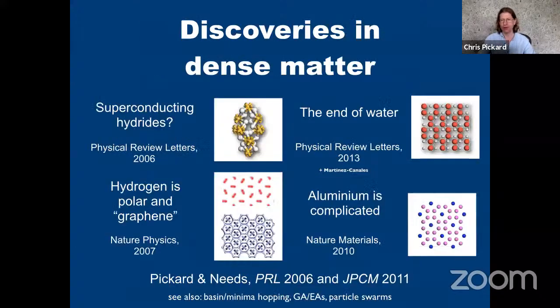So here's a sort of roll call of the early flush of success we had with this method. When we started out, it seemed like pretty much everywhere I pointed this code, I was finding new and surprising things. For example, we have generated probably still the best candidate phases for high pressure hydrogen. I found that if you squeezed water to high enough pressures, it actually decomposed. I'll show a little bit more of that later on.